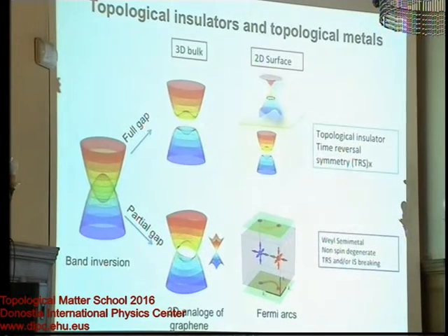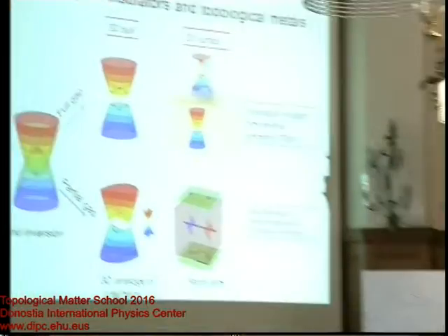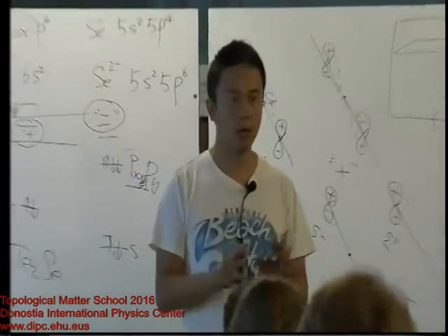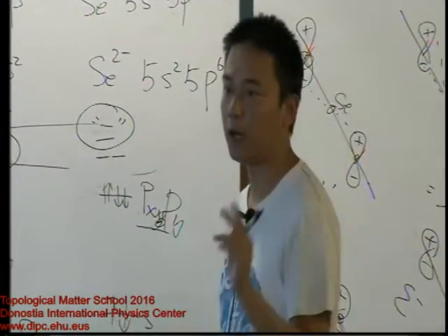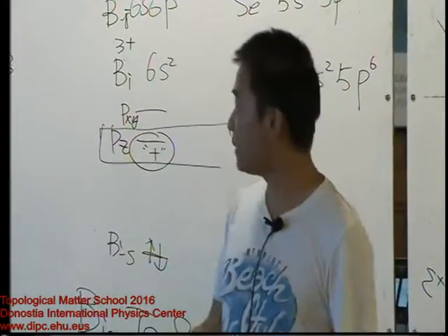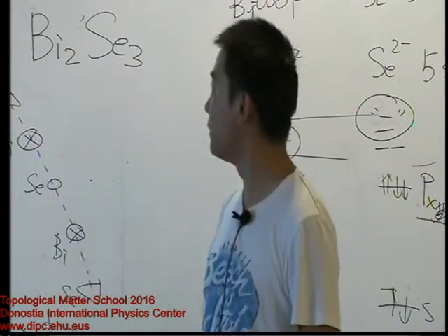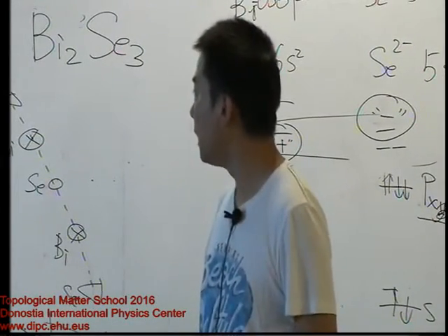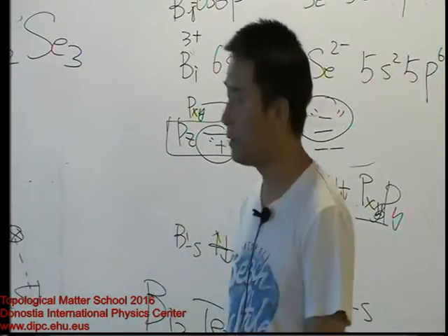And about the consequence, this kind of special semi-metal, because of the band inversion, will also give you topological surface states. It's very robust, just guaranteed by the inversion. So this band inversion picture can explain a lot. As long as you figure out the inversion, then you can think about other symmetry or other possibilities. And then you can easily address where the surface state is, whether it is robust, and in which case you can kill it or protect it.